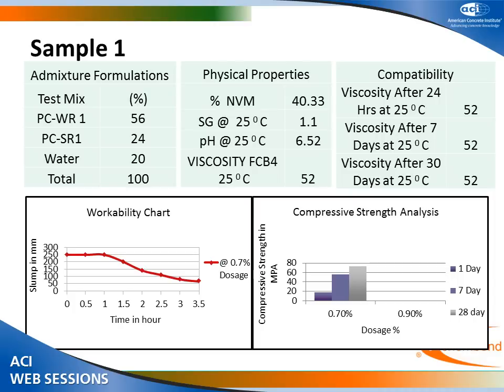Compressive strengths you can see at around 70 plus on 28 days, and on the first day it is around 17 to 18. Again, we have checked the compatibilities in two aspects. One is no separation up to 1 month, and then stability in the viscosity of the mix. So here it is stable because basically it is a polycarboxylate mix.